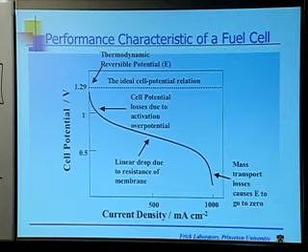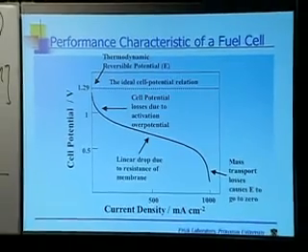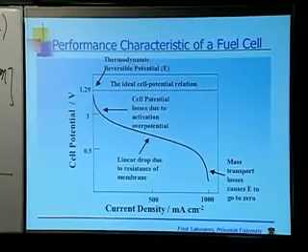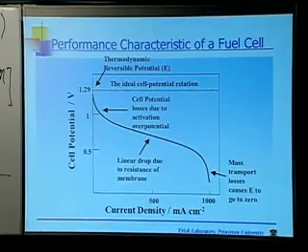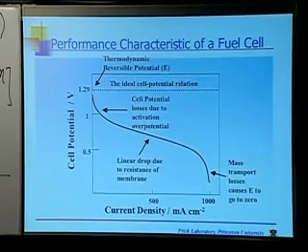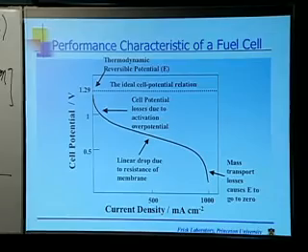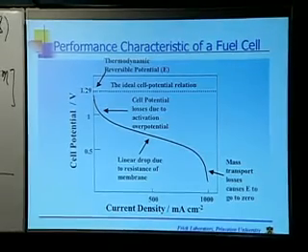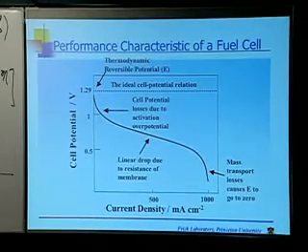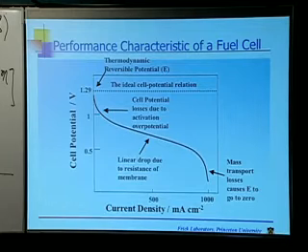That is, if I get some hydrogen moving over to my oxygen electrode, then I get the chemical reaction, hydrogen plus oxygen, just happening at the platinum sites there, and it doesn't get counted in my external circuit here. So I have some crossover loss to start with. I also may have some intrinsic resistances that show up at very, very low current densities, and that gives rise to a loss. So I start to pull current. Here I lower my resistance, in other words, my external resistance, and I see a very steep drop-off in my potential as I do it.